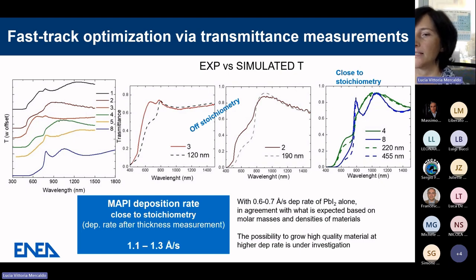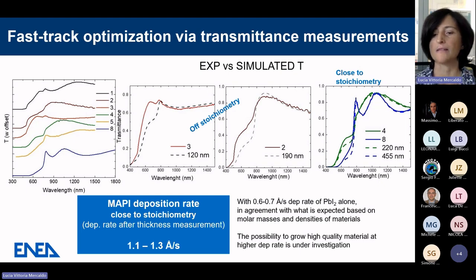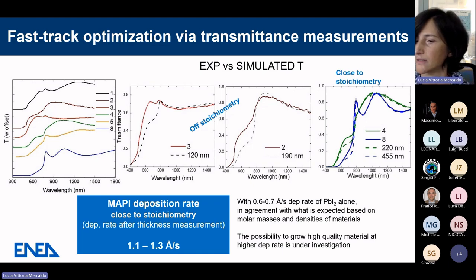And so we can easily see that by comparing experiment and simulation, it's clear when we are really off stoichiometry or close to stoichiometry. And we have reached a condition where the real deposition rate for methylammonium lead iodide is around 1.1, 1.3 angstrom per second when starting with the deposition rate of lead iodide alone, that is around 0.6, 0.7 angstrom per second. These numbers are in agreement when we consider molar masses and densities of materials. And we are now exploring the possibility to grow high quality materials also at higher deposition rate.